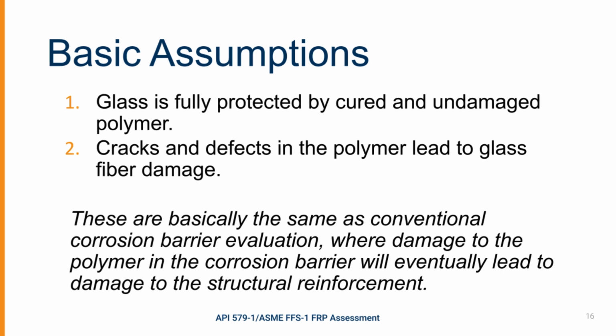The basic assumptions are that the glass is fully protected by cured and undamaged polymer. That's what we want. We always want the glass to be protected. And the cracks and the defects in the polymer, this is the damage, lead to glass fiber damage. This is completely consistent with corrosion barrier inspection that's been practiced for many, many years. As soon as the corrosion barrier is damaged, we're not sure what the damage to the polymer in the structural layers has extended to. So we very quickly say, well, the corrosion barrier has to protect everything, so we will call this not fit for service. That is not precisely true. It's when the polymer, even surrounding the structural glass, is no longer protecting it. And that's the thing that we're calculating on and do measure.